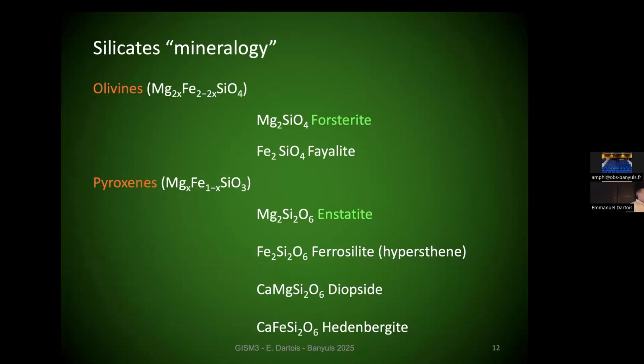The silicate mineralogy is much more complex than these 2 ones. And of course, there are flavors even within these silicates. If you go to the so-called magnesium pole of olivines, you would get Mg2SiO4, so-called forsterite. You may have heard about it. If you had only iron, it would be fayalite. You're not supposed to find this in space, with that amount of iron. And for pyroxene, again, you have different poles, enstatite and hypersthene or ferrosilite. And you can also add other elements that are less abundant to form diopside and hedenbergite.